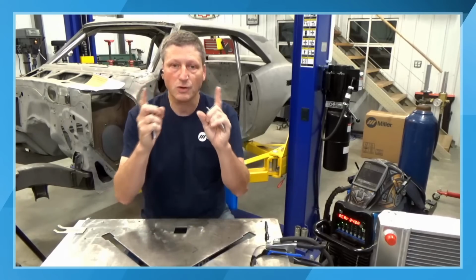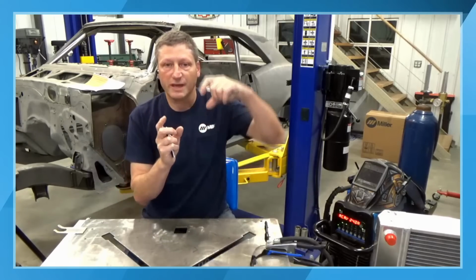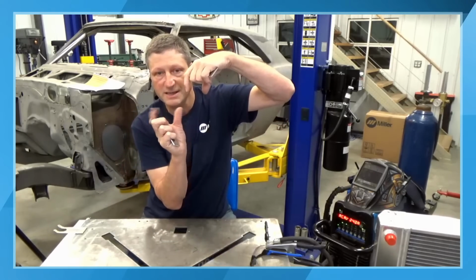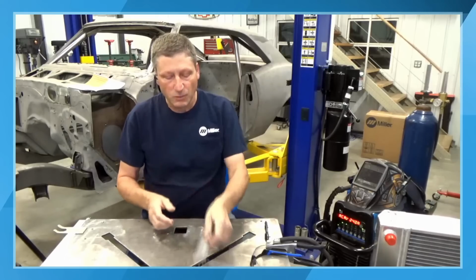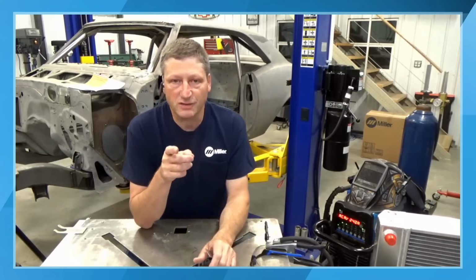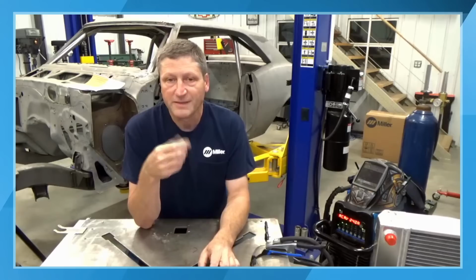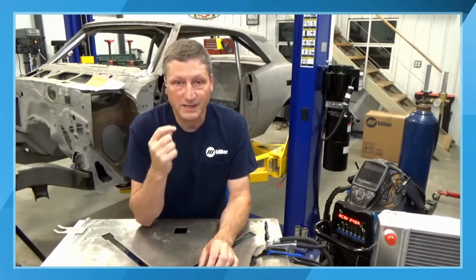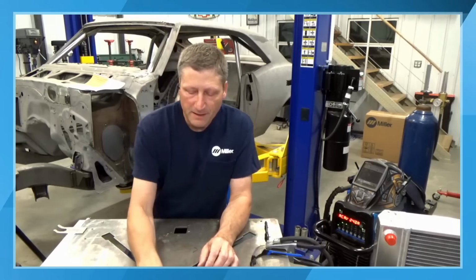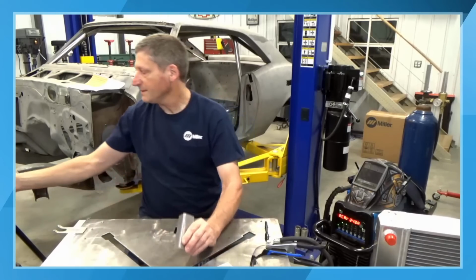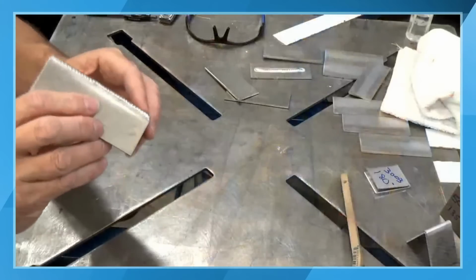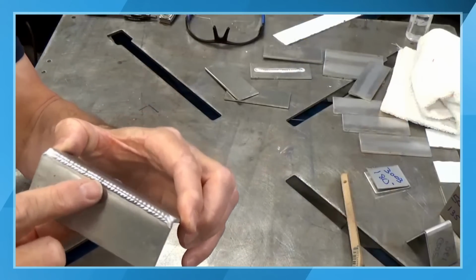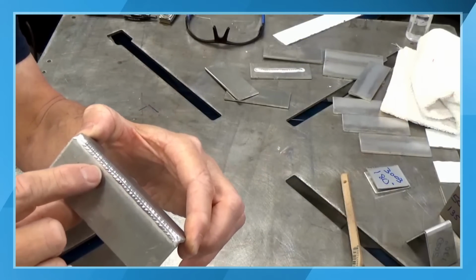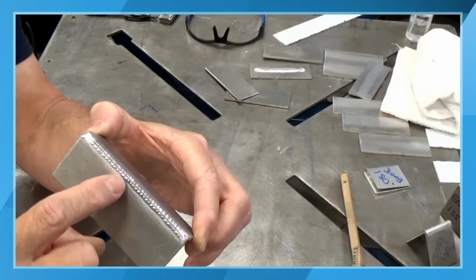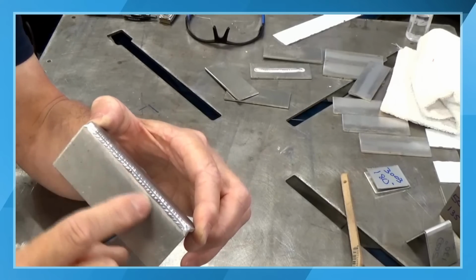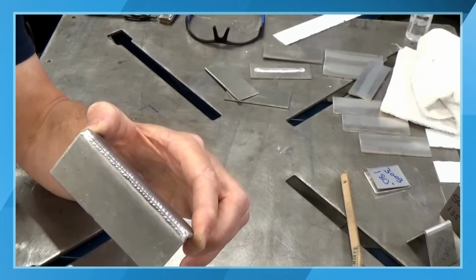Balance can control those times so that I can adjust the positive side of the AC and the negative side of the AC. And what that does is it changes that etching zone on the aluminum. That etching zone is that white area next to the weld puddle. And you basically need to see a little bit of that white on that weld puddle so that you know you've cleaned enough. So you see just on the edge of this weld bead, this puddle here, I've got just a little bit of that white area.